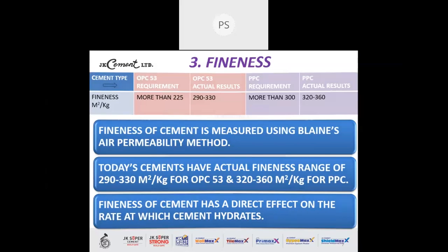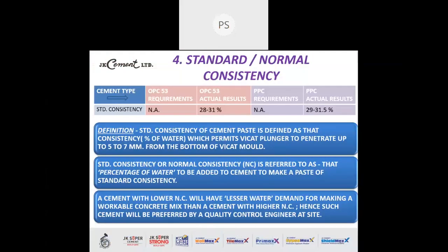Now the fourth and very important parameter that determines the final water requirement of the cement paste is the standard or normal consistency. For OPC 53, the IS code does not mention any parameter. The actual result range for standard or normal consistency is between 28 to 31% in India. The PPC requirement is again not available in India. In PPC, the result range is between 29 to 31.5%.